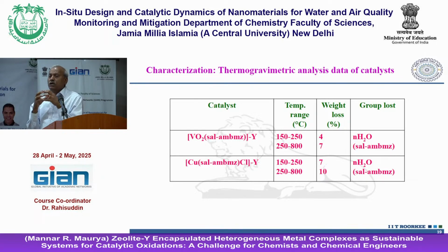Still, a lot of water molecules are trapped inside and cannot come out unless you heat at higher temperature. So in the beginning the water molecules are coming out. After 250, the loss is definitely due to decomposition of the metal complex. That can give you an idea about the decomposition of the ligand, and whatever percent you are getting is due to ligand present in the cavity, if it is perfectly washed and all unreacted or free ligands are removed from the mixture.